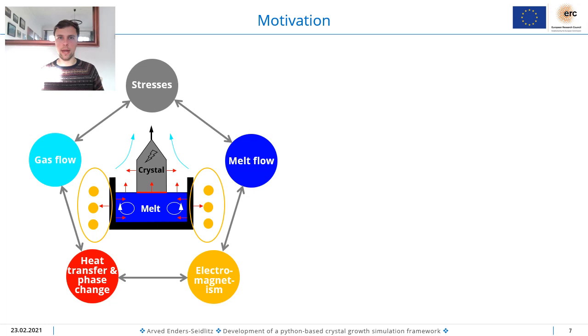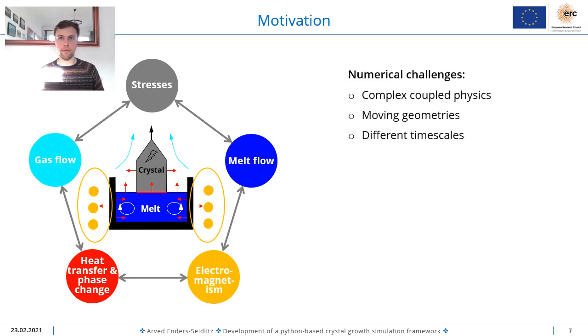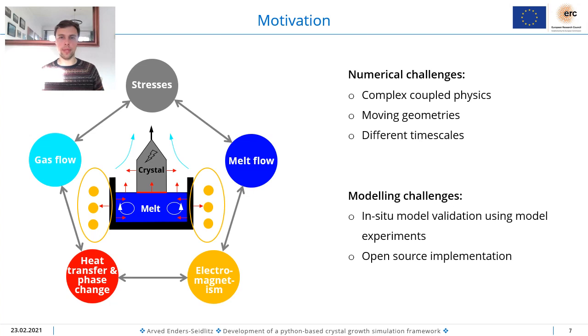Looking at the physics, you can see that there are many processes involved in the crystal growth process — for example, thermal stresses inside the crystal, the gas and melt flow, the electromagnetism of the induction heating, and of course the heat transfer and the phase change. From a numerical point of view this is challenging because of the complex coupling of the different physics, the moving geometries, and the different timescales — we can see a very high flow velocity compared to the low growth velocity of the crystal. From a modeling point of view, this is challenging because of the mostly missing in-situ measurements for validation, and in our project we took the challenge to implement the whole simulation in open source software.